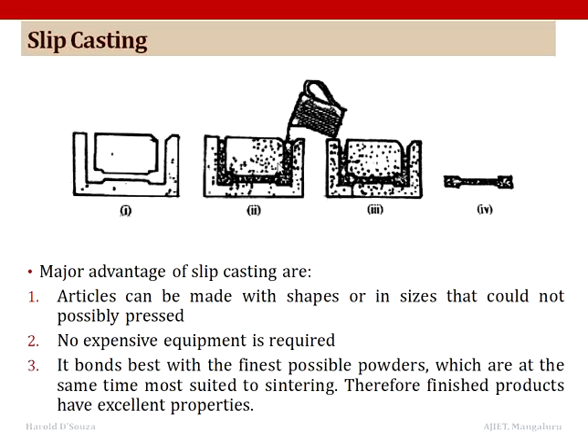Metal powders may be slip cast into the desired shape using a porous mold prepared from plaster of Paris. Now, the mold has the negative shape of the article to be cast. The different steps in slip casting are shown schematically in the figure, which shows the assembled plaster mold, filling the mold and absorption of the water from the slip into the porous mold. Now the excess water can also be removed by external pressure. The finished piece is then removed from the mold and trimmed. Sometimes a mold release agent such as oil, starch or graphite is used.